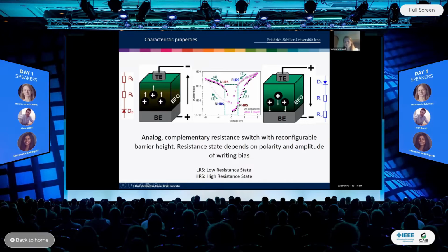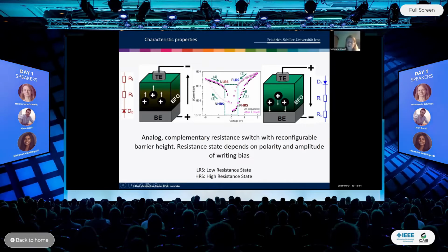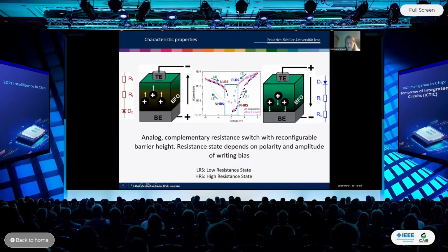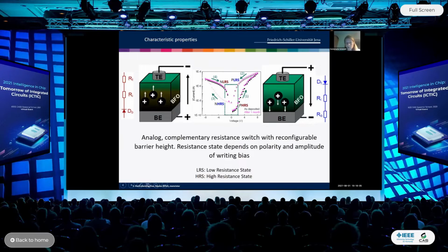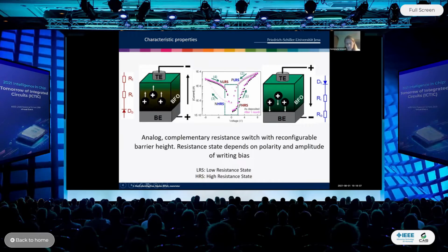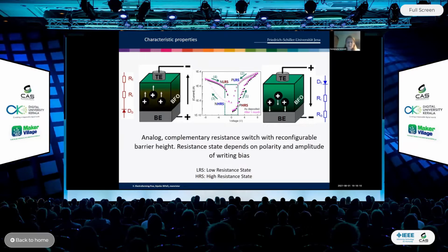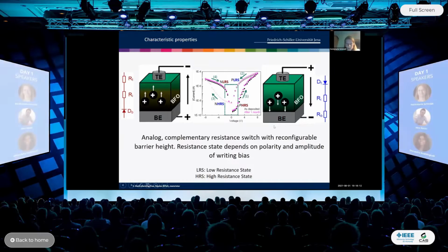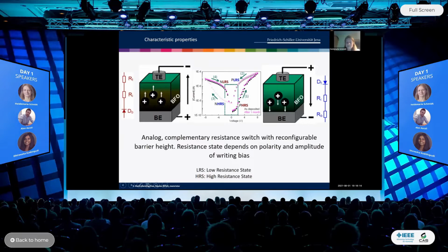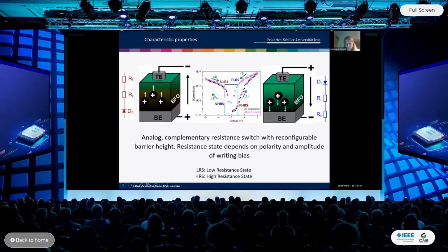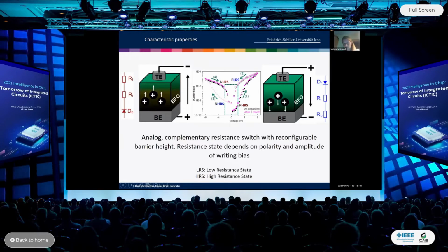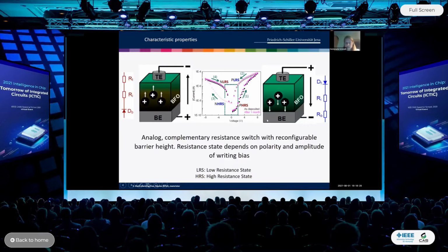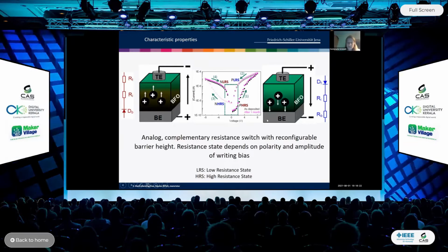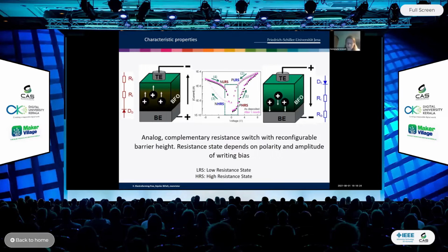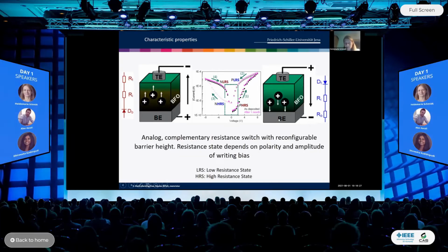On the other hand, the polarity of the readout also determines whether we can read out a large or a small readout current, right? And this is also very important. So we have in total 4 states we can reconfigure in the system. And this is very unique because with 4 states you can make all the 16 Boolean functions and emulate them with a simple passive device.